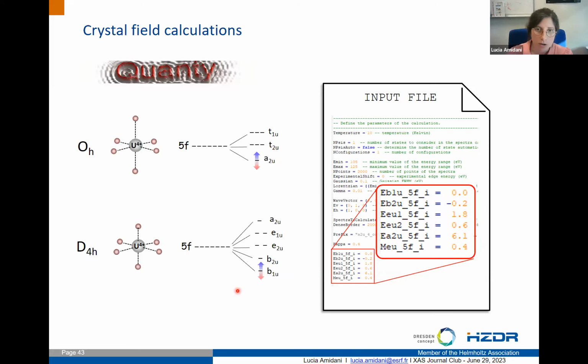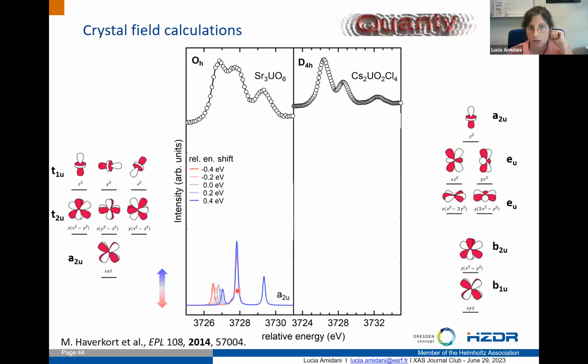And this we did because we wanted to tune the energy of a single group and see what was going on in the spectrum, basically like twiddling here to see what in the spectra changes. And this sort of small game actually confirmed our interpretation based on the DFT, because when we are in the uranate and we start to move the energy of this orbital, we get that the first peak is mostly shifting.